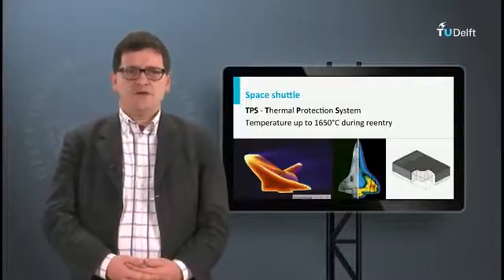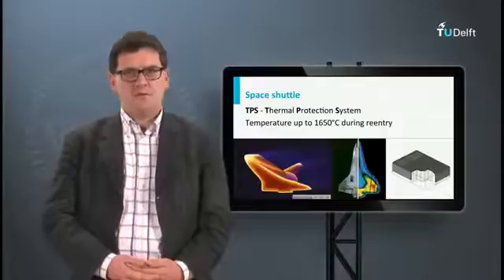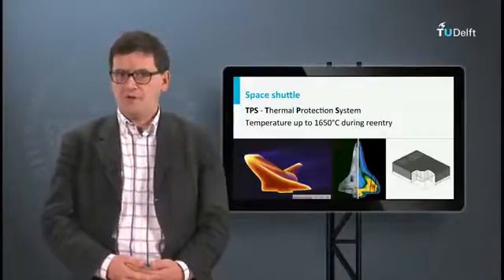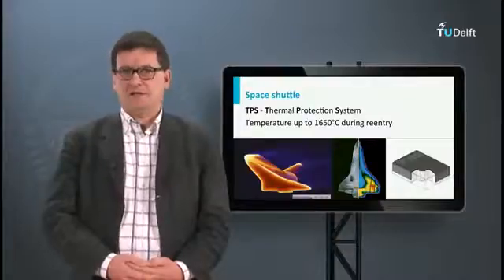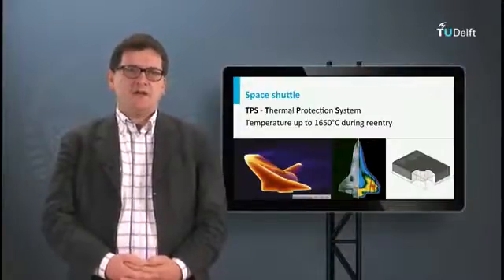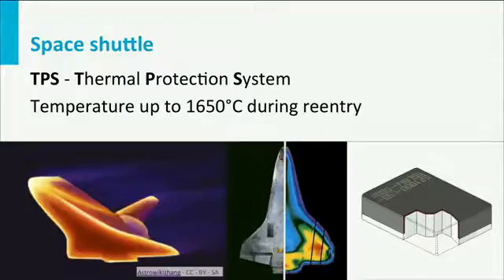The space shuttle used other materials to cope with the high temperatures. Its thermal protection system consisted of special carbon-carbon composites, special tiles, and heat blankets. Each area had its own material. The hotter sections, the nose and the leading edges, were made of carbon-carbon composite, a hard but brittle material that can cope with temperatures exceeding 1650 degrees Celsius. However, the brittle nature of the material also took its toll when the shuttle Columbia disintegrated during re-entry, because the leading edge was damaged. Another famous material applied on the space shuttle are the black tiles.